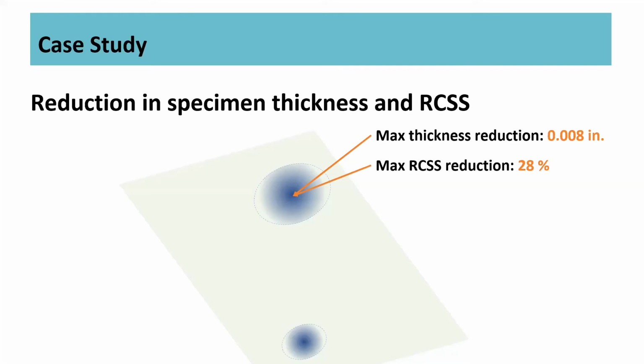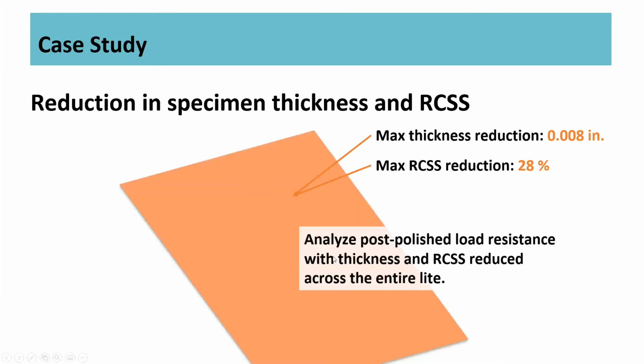For our analysis purposes, what we decided to do was, it gets kind of iffy to try to do plate analysis with a varying thickness in the middle of it. And we felt like that's probably just unnecessarily complicated. Why don't we just assume the entire plate now is the reduced thickness and has that reduced RCSS, and we'll do our analysis based on that information. This way we know that whatever number we're getting is likely way lower than it actually is, since often we're just doing a small area. And it's likely going to cover any other secondary effects that our relatively simplistic approach so far addresses. We feel like we're in pretty good shape by making this assumption.